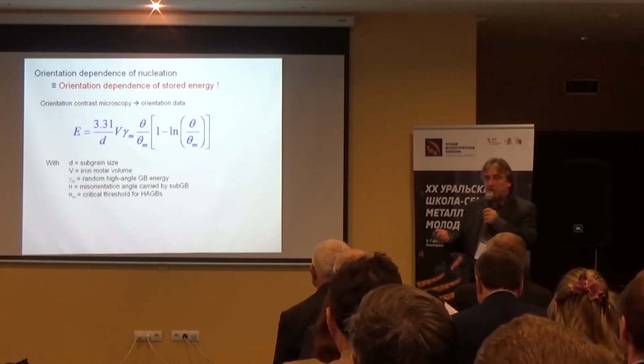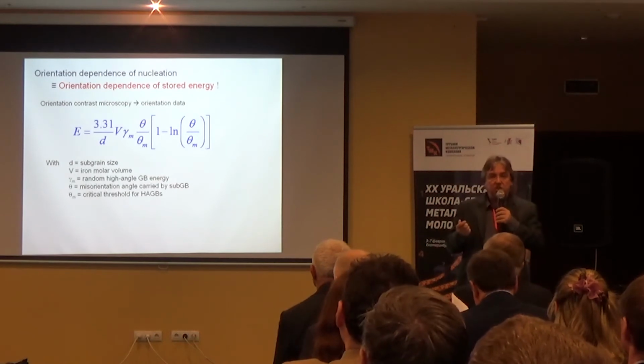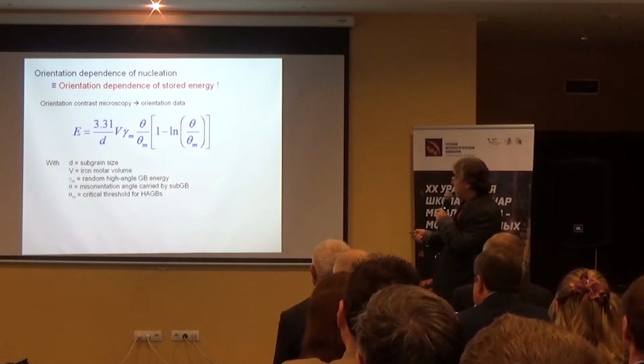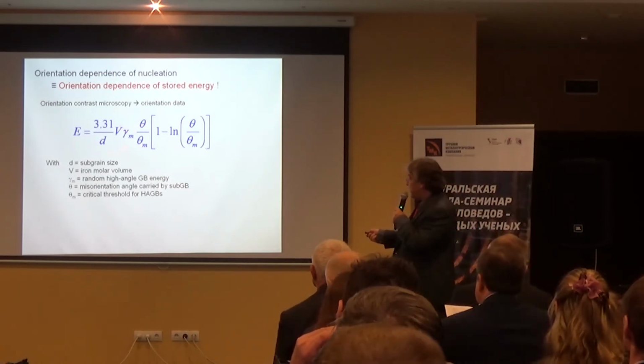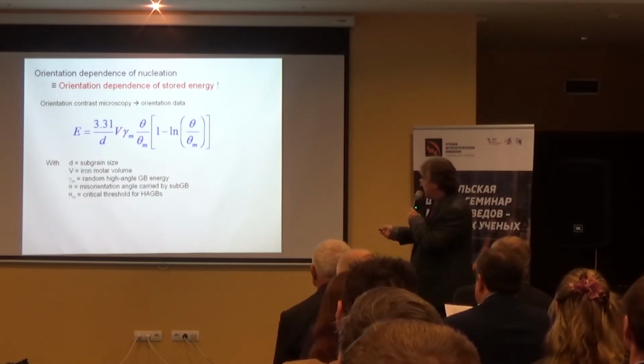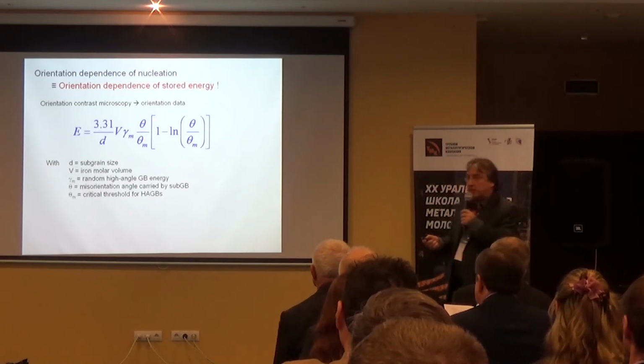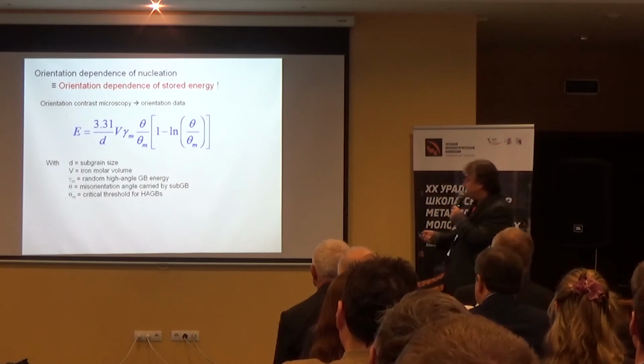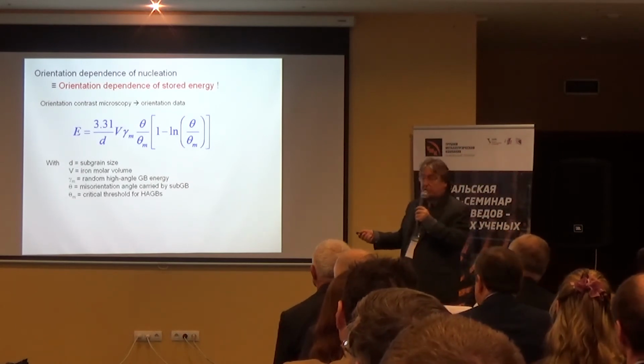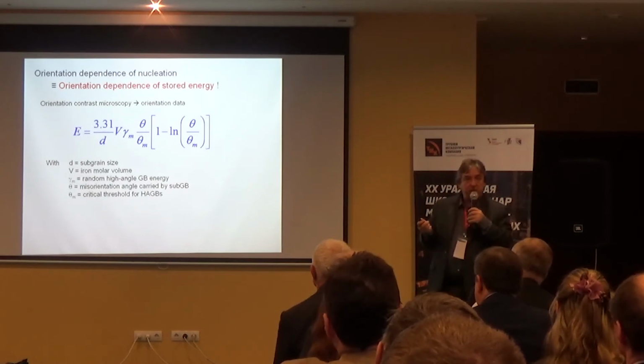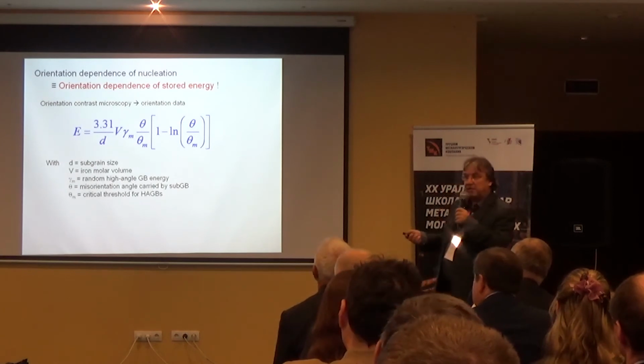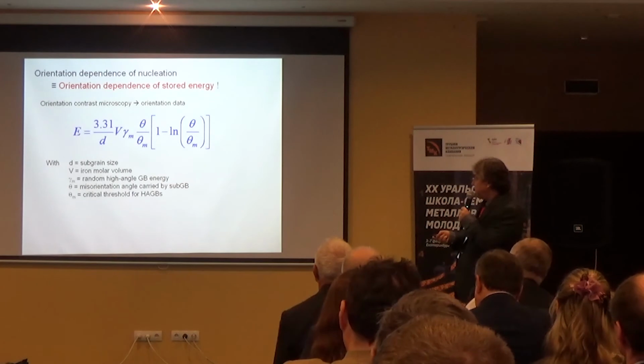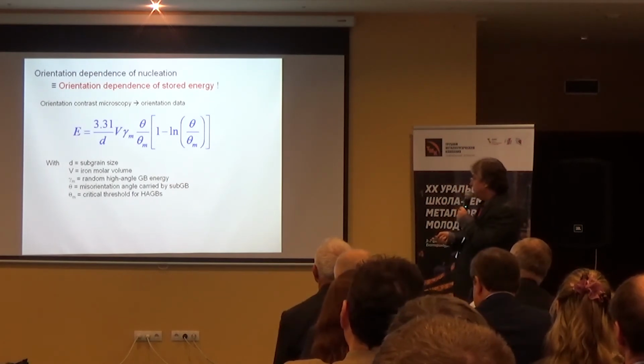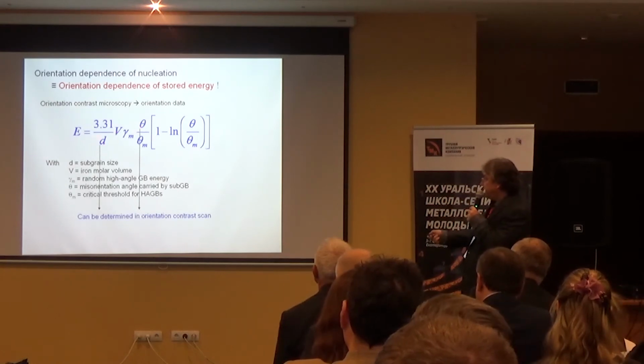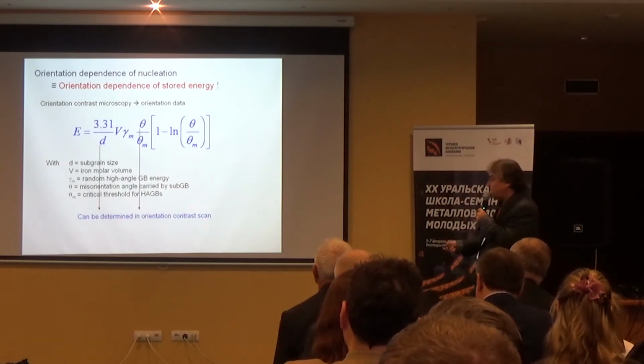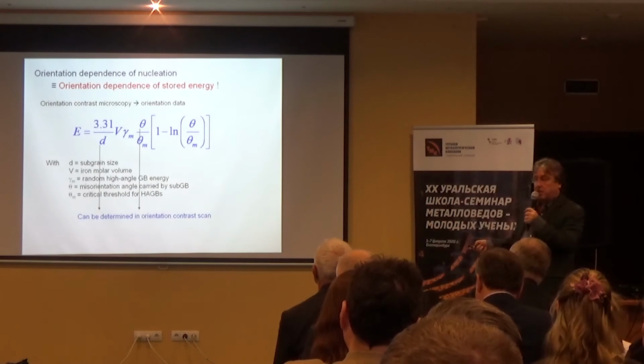Now there are various ways to extract stored energy information from EBSD data. One of the ways is to link the cell size, D, or the subgrain size, and the misorientation between cells to the stored energy. This is the famous Read-Shockley relation, which gives you the stored grain boundary energy as a function of misorientation and cell size for low energy, low angle grain boundaries. And this data can be obtained from EBSD data. So they can be determined from orientation contrast scans, and we can calculate the stored energy.